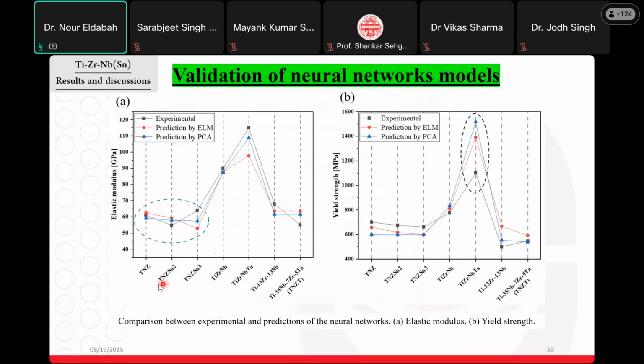Here you can find a comparison for the proposed three alloys. In the black line here, you will find the inflection in the elastic modulus, but the neural network cannot catch this type of inflection. The extreme learning machine, the first neural network, cannot catch it, and it expects that adding more tin will reduce the elastic modulus of the alloy, whereas the feed forward backpropagation incubated with PCA mostly cannot detect any changes in the elastic modulus. And this is because, as I told you, incubating PCA in your machine learning algorithm will affect the sensitivity. It cannot differentiate between these small differences in chemical composition.